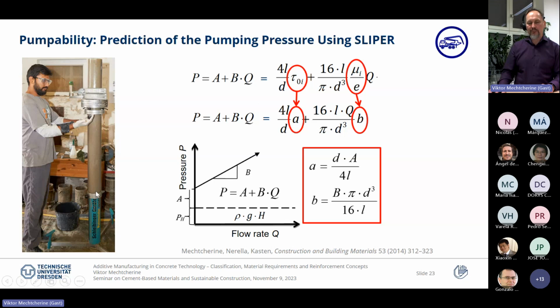So there's a sensor placed here at the bottom of the concrete column, and you measure the speed with which the pipe is moving, and you can change the speed by attaching more and more weights to this pipe. So basically what you get is a relationship similar to what Nicola showed in his presentation. Just in this case, it's pressure versus flow rate, and what we want to get here is a possibility to predict this relationship.